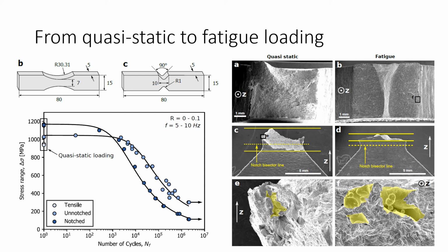And we see that in the static loading, the fracture surface is ranging across the notch bisector line, while for fatigue it's not ranging across. Its failure is just occurring from the downskin region. So this indicates that fatigue is controlled by the small defects in fatigue loading, while in static loading those are not as dominant.